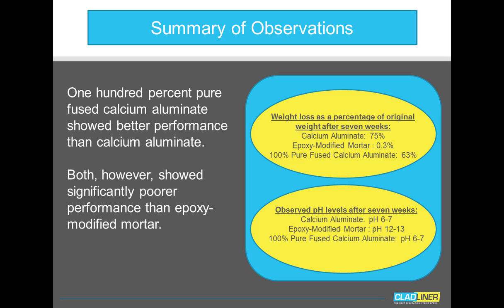So, our summary observations from this study showed the 100% pure fused calcium aluminate showed better performance than the traditional calcium aluminate. Both, however, showed significantly poorer performance than the epoxy-modified mortar. So if we look at the weight loss, first of all, again, after 7 weeks, let's recap. Calcium aluminate lost 75%. Pure fused lost 63% of its weight. The epoxy-modified mortar lost 0.3%.